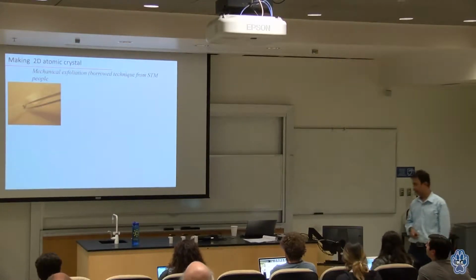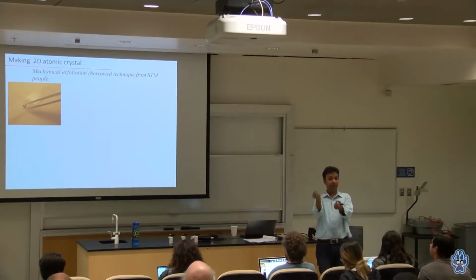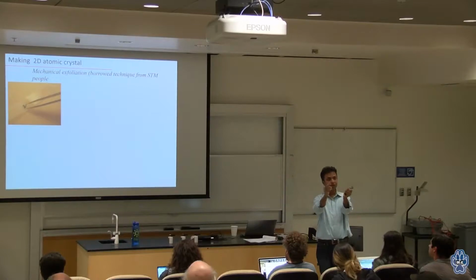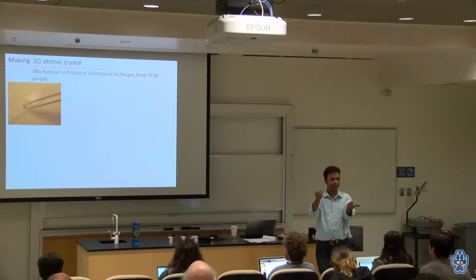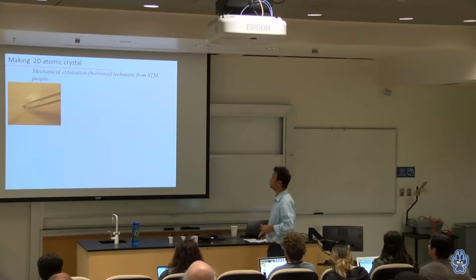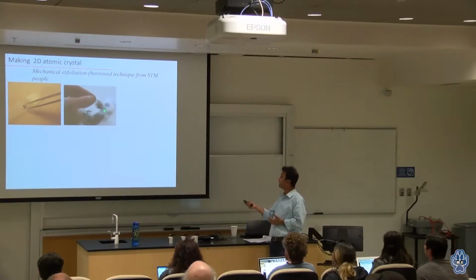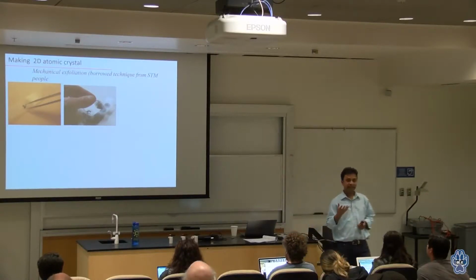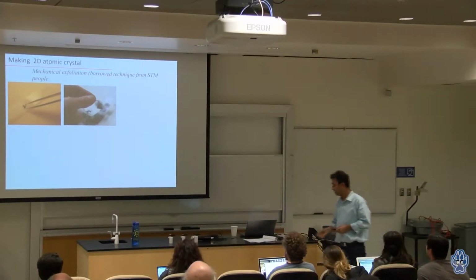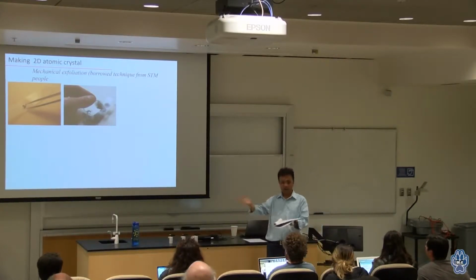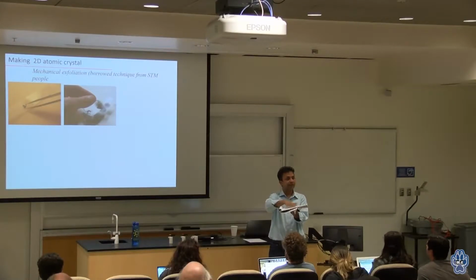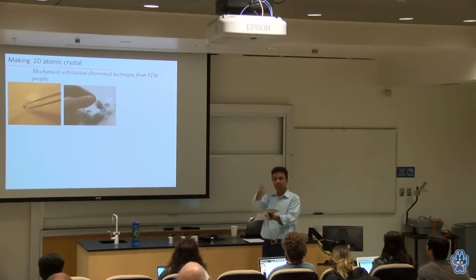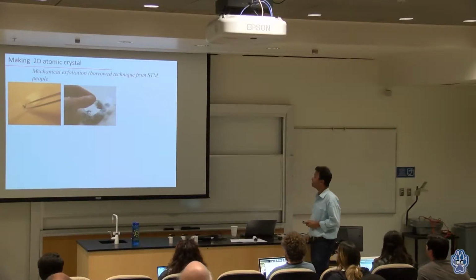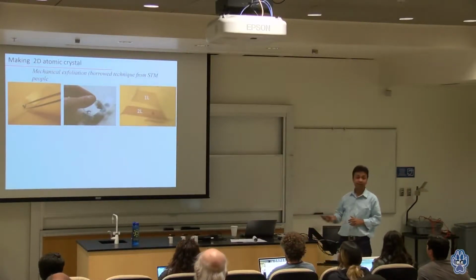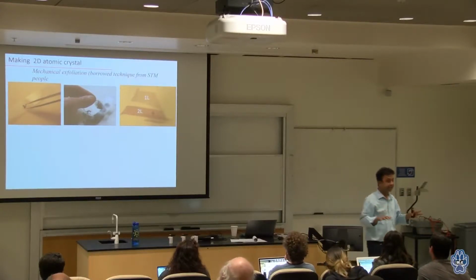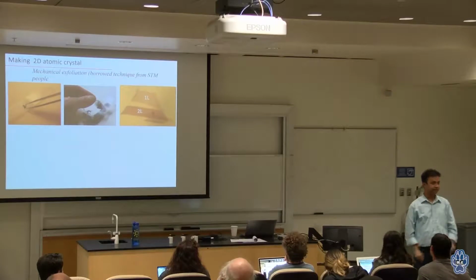So how did you start? You start with a Scotch tape, you put graphite flakes on the Scotch tape, and you do peeling off, layer by layer, because it's nothing but all these layers attached very weakly. Sometimes you will see this ugly Scotch tape, but it contains all these flakes in it. You put that Scotch tape on a substrate, and you slightly scratch it, and then you remove the Scotch tape. If you look under a microscope, you will see a really very transparent layer, which is actually made of one carbon atom thick.